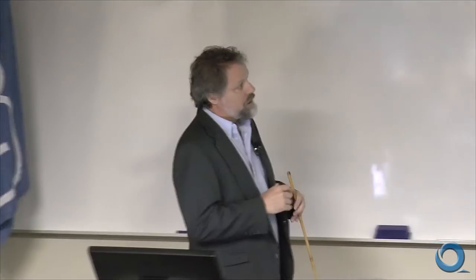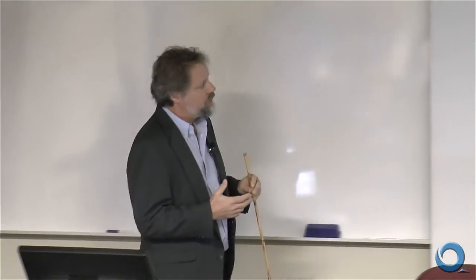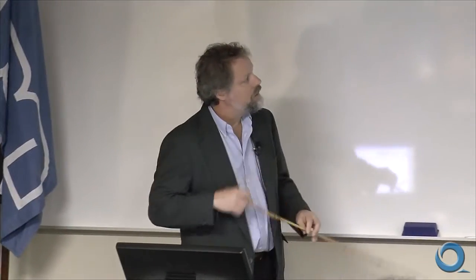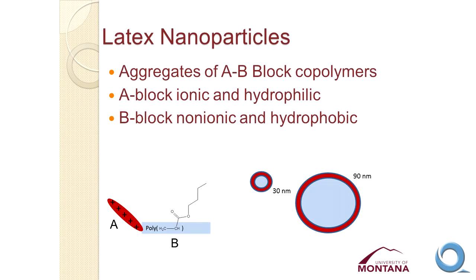The nanoparticles that we're talking about, we synthesize at the University of Montana, and they are aggregates of an AB block copolymer. So it's a polymer with an A block, which is ionic. In this case, I've shown positive signs. It's a cationic block on the polymer. And then a second block, which is hydrophobic. In this case, I've shown butyl acrylate as the hydrophobic monomer.